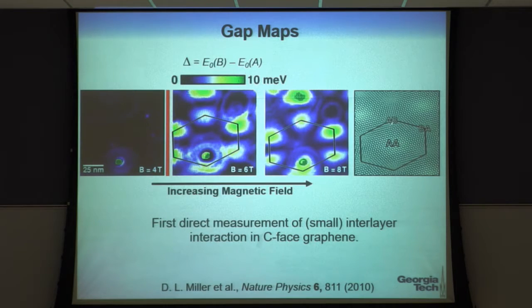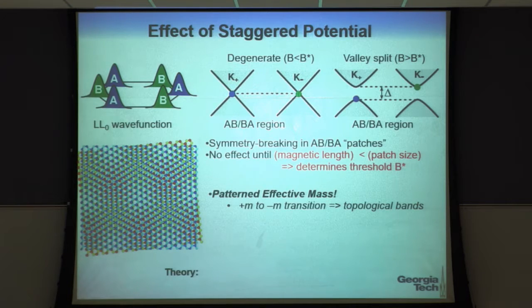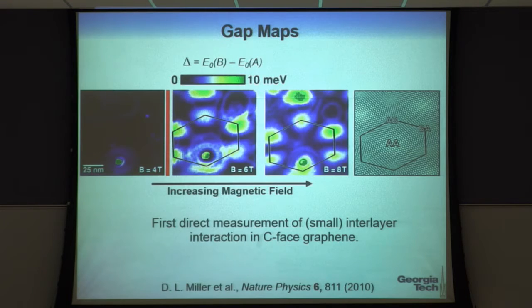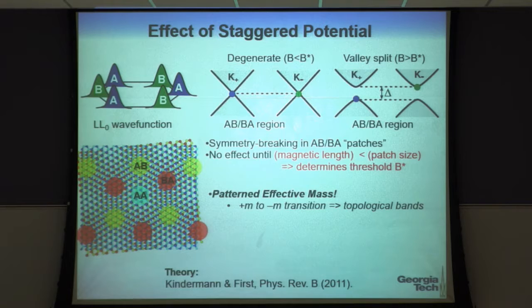consequence of this coherence, the alignment of AB or BA. And if you think about it, this dark region in between, in fact, is where you have a transition from blue here, green there, to blue here, green there. And that transition, in fact, is equivalent to looking at positive effective mass, negative effective mass, right? Holes have negative effective mass, electrons have positive effective mass. But here I change the sense of which is which by changing the sense of the A and the B atoms. So effectively I have a pattern effective mass that goes from positive to negative, and in between, in these little lines that go in between, then in fact you would expect that in these dark regions there is actually a topologically required state, a band crossing in graphene itself. Marcus Kindermann is responsible for most of the theory of that.